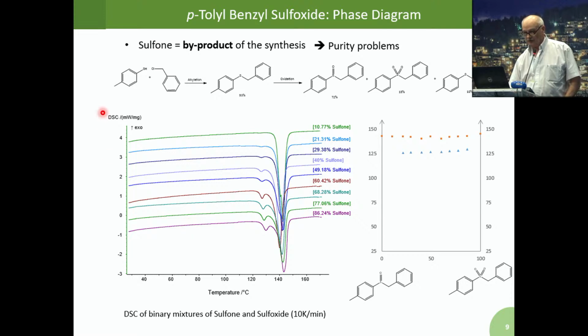First, let's go back to the synthesis of this molecule. So it's pretty easy, with two steps. So starting from the thiol here, we condense with the chlorine derivative here. So this alkylation is within good yield, and we obtain the sulfide that you can see here. And the sulfide needs to be oxidized softly to obtain the sulfoxides. Okay, so the R and S sulfoxide, only, you know, a racemic picture is presented here.